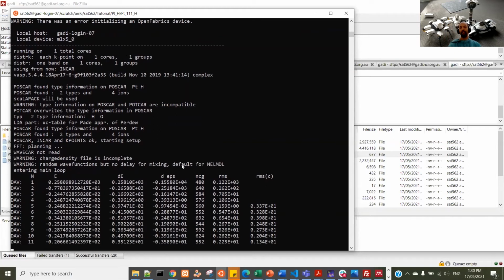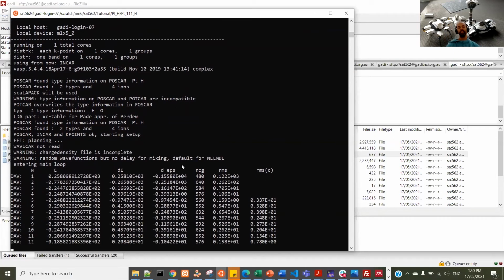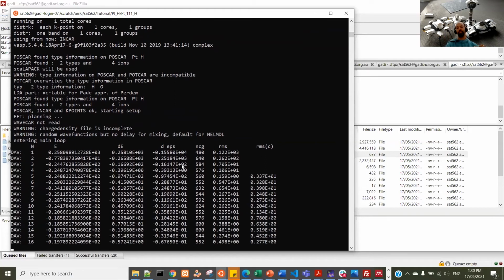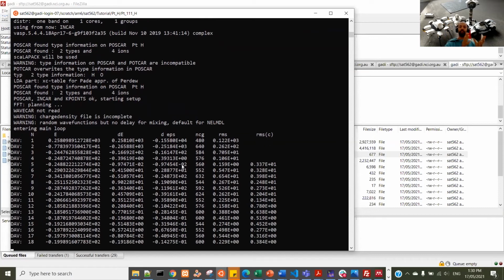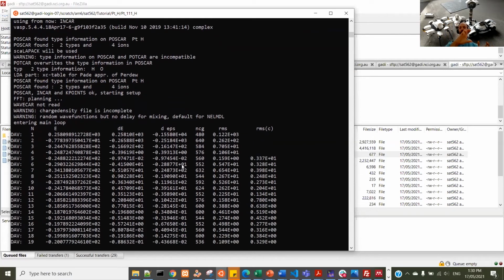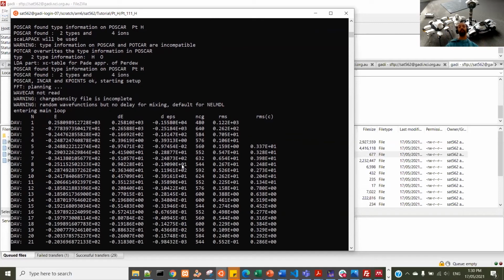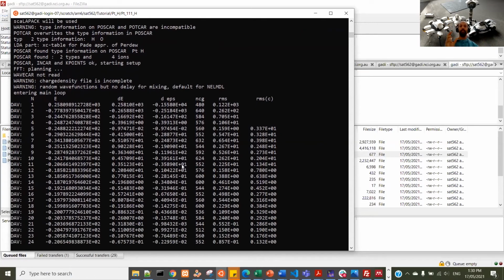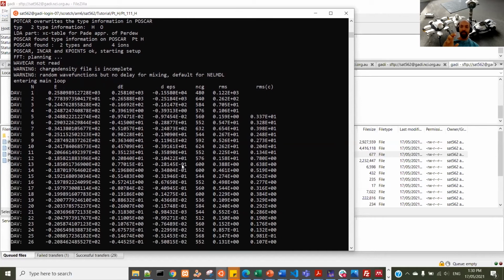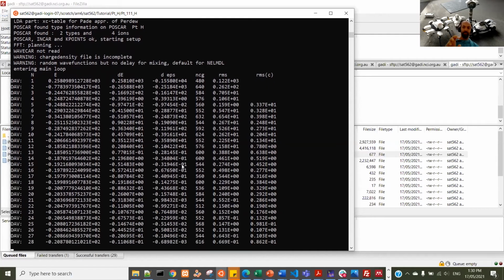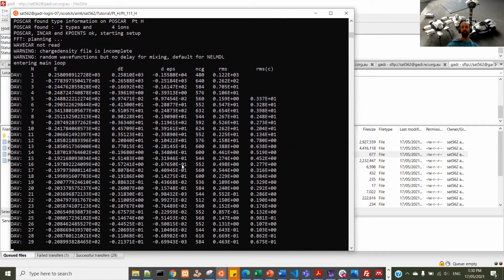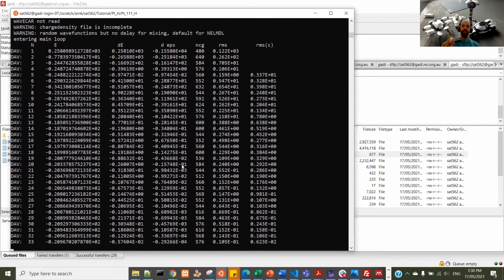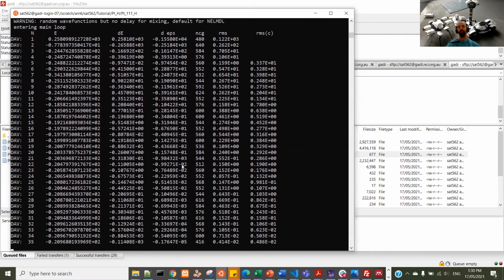And once that is done, we get the total energy for adsorbing an H atom on top of the platinum slab. Now, in order to get the adsorption energy, again, going back to the second tutorial, in that tutorial we use the formula for that calculation. The total energy for the H on top of platinum, we get that number, and then we subtract from this number 2 numbers. We subtract the total energy for a platinum slab without anything, the pristine platinum slab that we already calculated in the folder PT111, minus the total energy of an H2 molecule divided by 2.